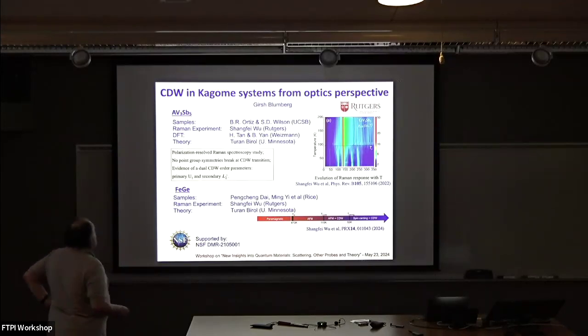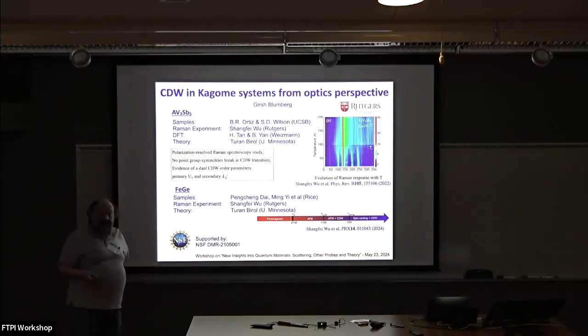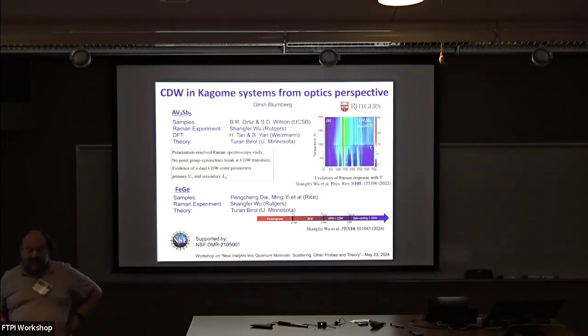So we did a polarization resolved Raman study. As an output of this measurement, which in this case is all phononic, we are not looking at electronic response, we're really looking only at phonons. We are finding the symmetry of the modes, and there are obvious allowed modes, and then the transition due to broken symmetry. New modes appear, and those are amplitude modes in some cases. So we were dealing with the entire zoo, and the unit cell is pretty large, and we tried to make sense of the modes.